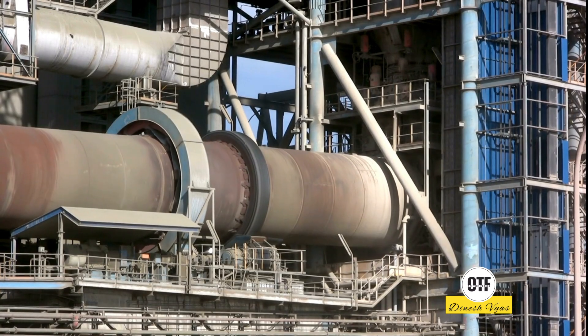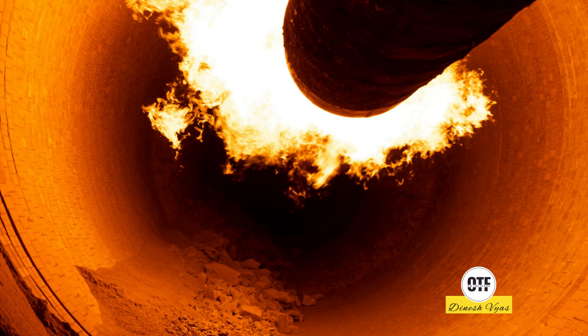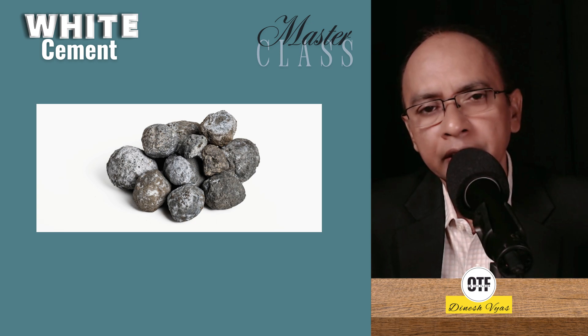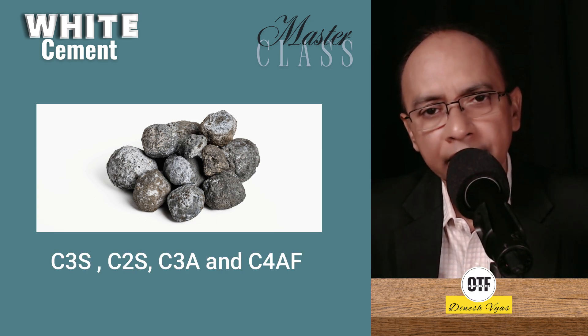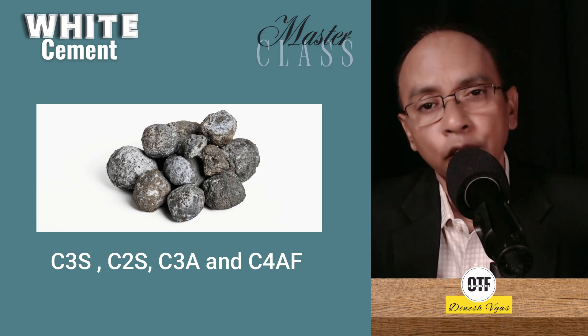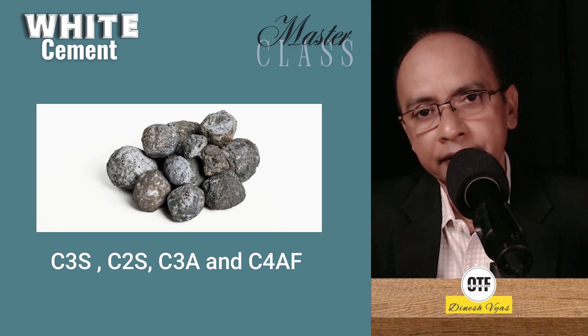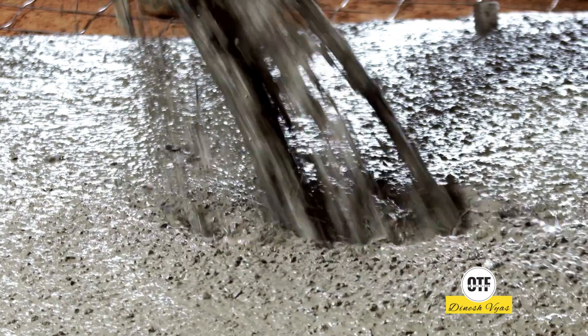All this material in powdered form is sent to the kiln, where at very high temperature, clinker is formed. Clinker means four basic elements: C3S — tricalcium silicate; C2S — dicalcium silicate; C3A — tricalcium aluminate; and C4AF — tetracalcium aluminoferrite. This last component, C4AF, is the main component which causes grey colour. The absence of the C4AF phase — what we call ferrite — is the main reason why white cement is white.